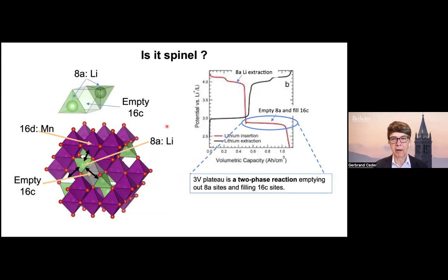So spinel, of course, is a very known lithium manganese oxide. Spinel is a very well-known cathode material. Here's the typical voltage profile. Commercially, only the 4-volt region has been used. And there was a 3-volt plateau that we could never use commercially because that's a two-phase reaction. That's why this is so flat. And a two-phase reaction, by definition, occurs inhomogeneously. So you get one part of the material that completely fills while the other one doesn't. And that causes enormous strain. And that's in part why the material degrades extensively.